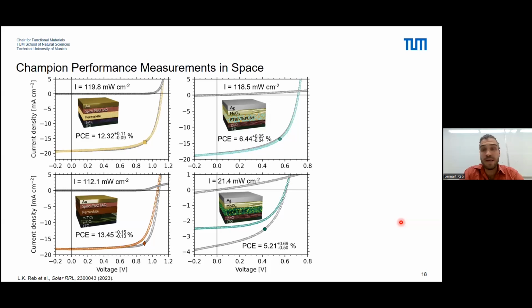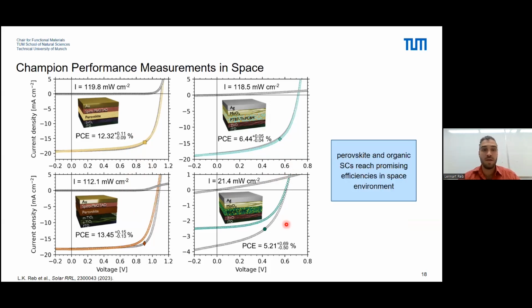strength. Okay, so this is the champion performance measurements in space for all these 4 solar cell types, where the perovskite solar cells reach efficiencies of 12 or 14%, and the organic one 6 or 5%. So they all reach the promising efficiencies in space environment. So these measurements are actually performed in space above 100 kilometers, and this after the travel to Sweden, after mounting them, the rocket launch, and also some environmental exposure.